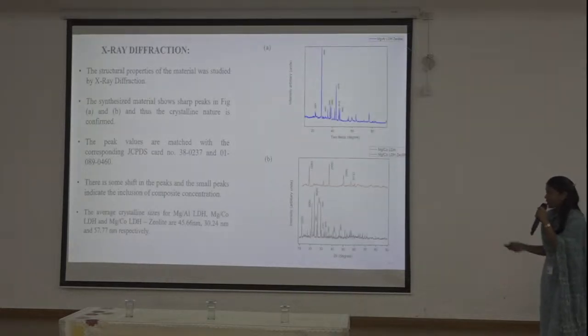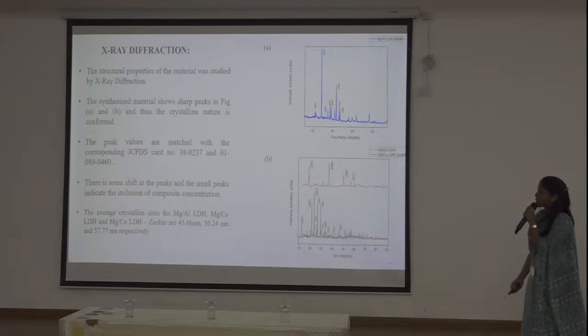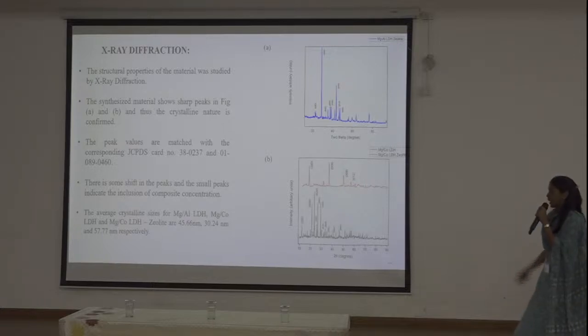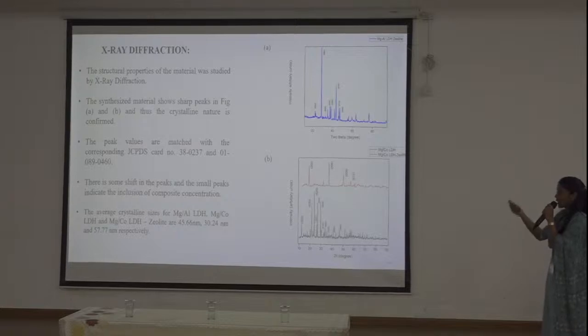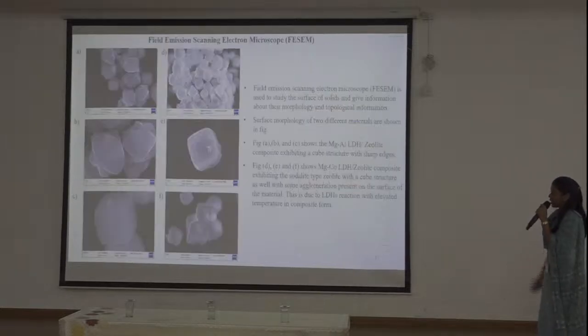X-ray diffraction analysis was taken to confirm the structural properties of the material, and the sharp peak confirms the crystalline nature of the material. We also calculated the average crystalline size.